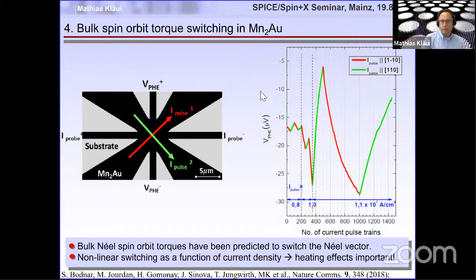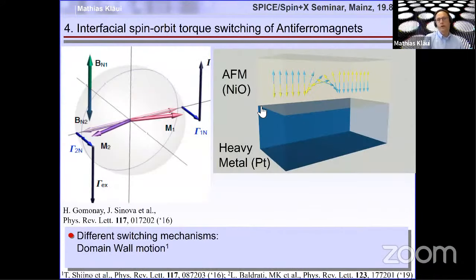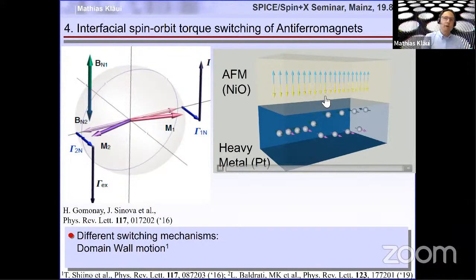Now, this is working for these very special antiferromagnets like copper manganese arsenide, copper manganese antimony, and also manganese two gold. But you'd rather like to have an effect that also works in systems that don't have this broken symmetry. For instance, for nickel oxide, which is a very typical antiferromagnet, you'd like to have a torque that is exerted on the spins that works even in a system where we cannot distinguish between the sublattices. And that was something that was predicted here by Helen Gomonay and Hiro Sinova, where if you put a bit of platinum below or above this antiferromagnet, then the spins are actually injected across the interface into the antiferromagnet, leading to a domain wall motion in the antiferromagnet.